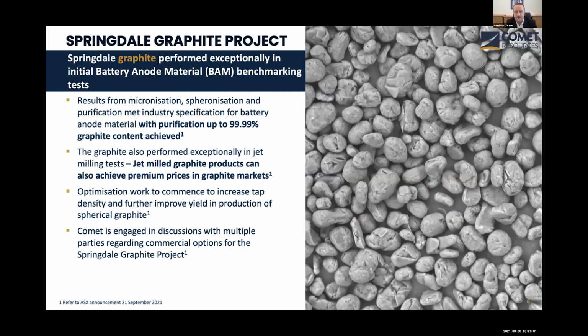Looking at the results from last week that you mentioned earlier, we've been doing metallurgical test work on the graphite for the last 12 months. The initial process was to see if we could create a high-grade concentrate. We were able to achieve that last year. This year we then moved on to creating a bulk sample of that. That takes quite a bit of time because the cells in the labs are quite small, so you have to run numerous batches. But we generated the bulk sample around about July.